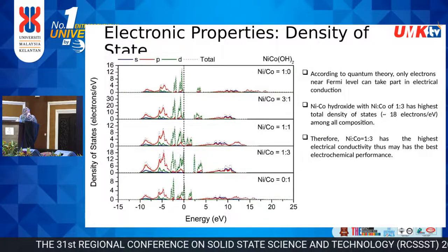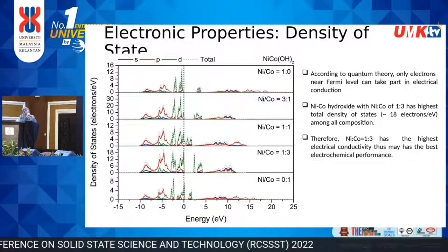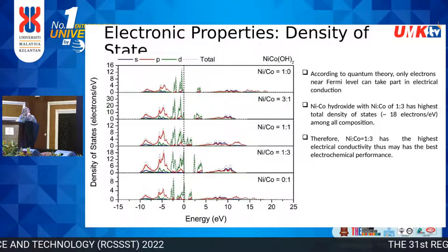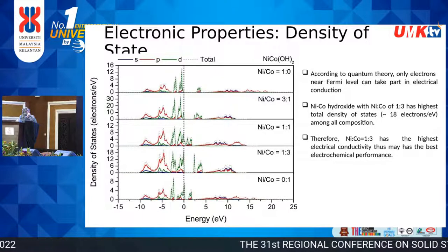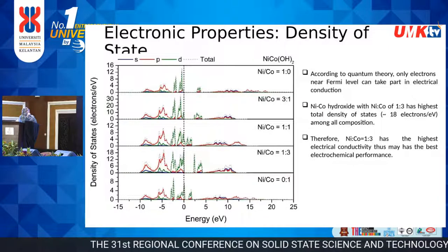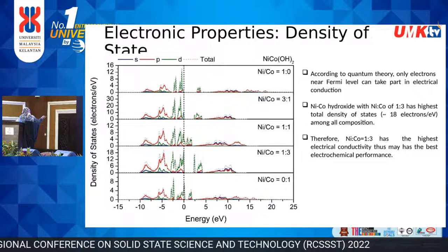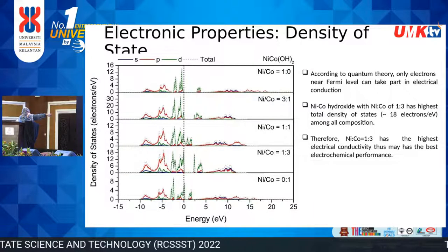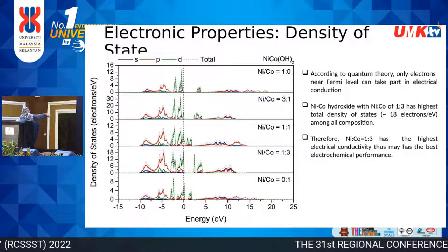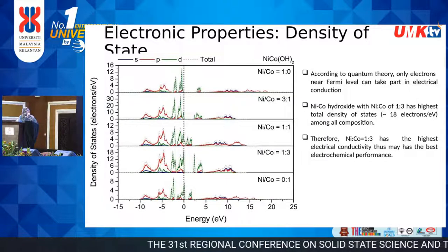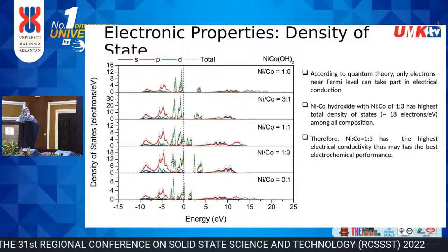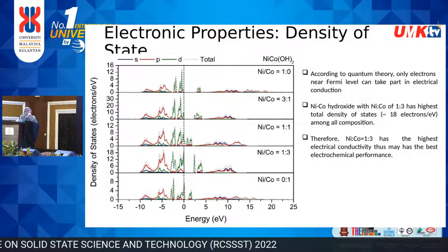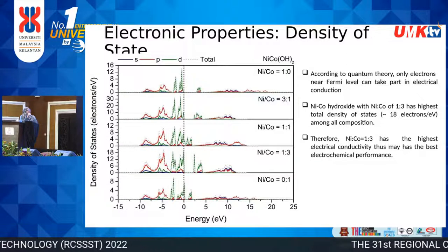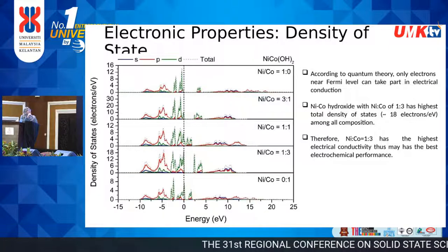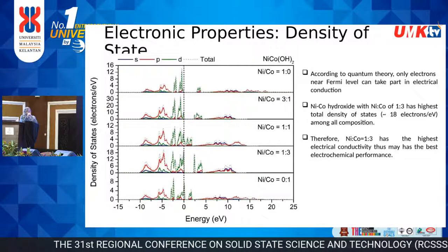This is the density of states. According to quantum theory, only electrons near the Fermi level can take part in electrical conduction. Nickel cobalt hydroxide with nickel to cobalt ratio of 1:3 has the highest total density of states, around 18 electrons per electron volt among all compositions. You can see that at nickel to cobalt ratio 1:3, we have a peak nearest to the Fermi level at the dotted line, so it has the highest density of electrons there. Therefore, nickel cobalt hydroxide with nickel to cobalt ratio 1:3 has the highest electrical conductivity, and this may have the best electrochemical performance for our supercapacitor.